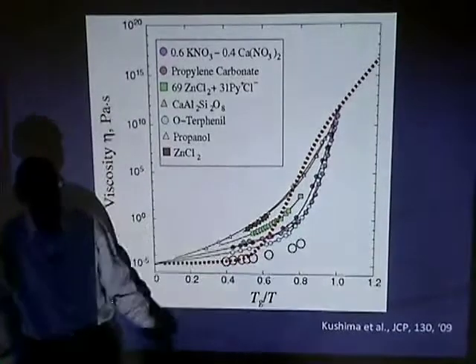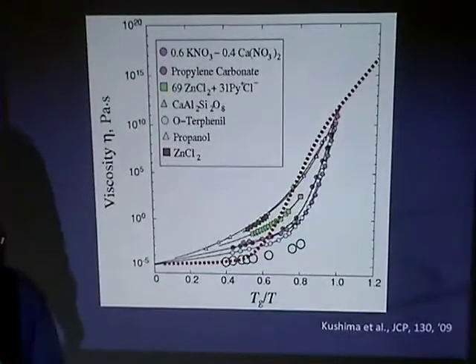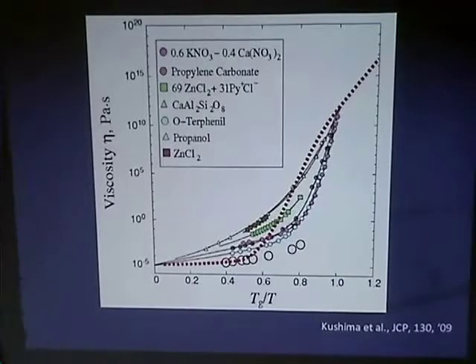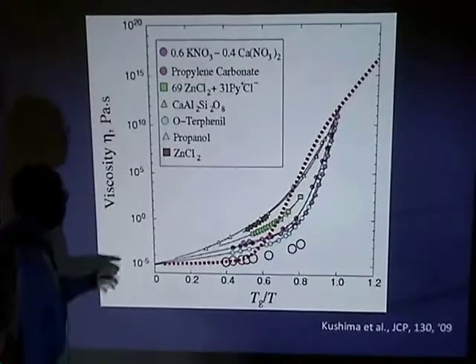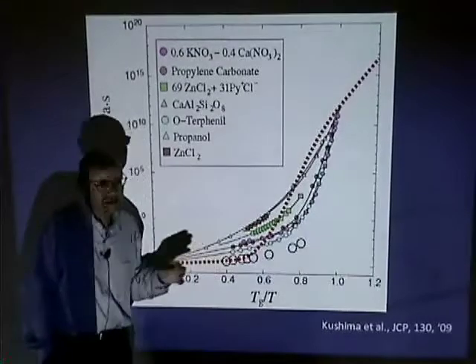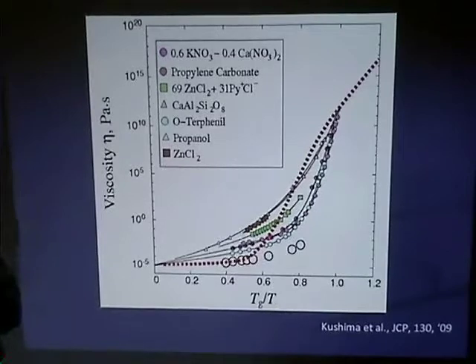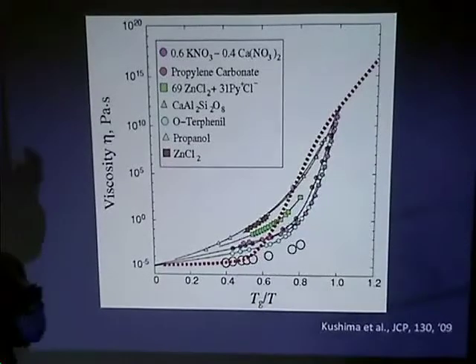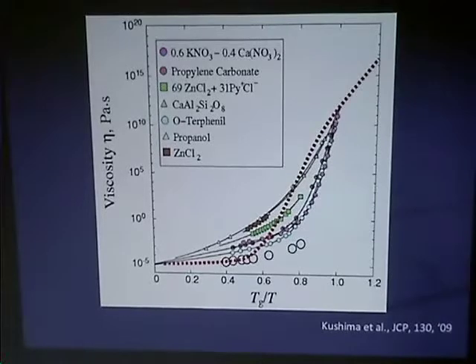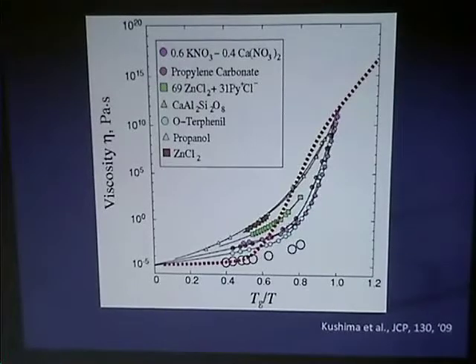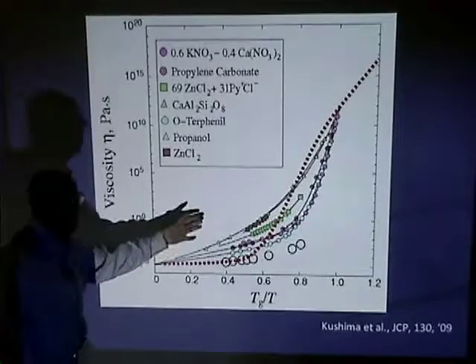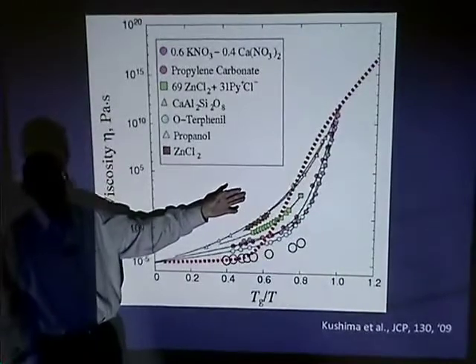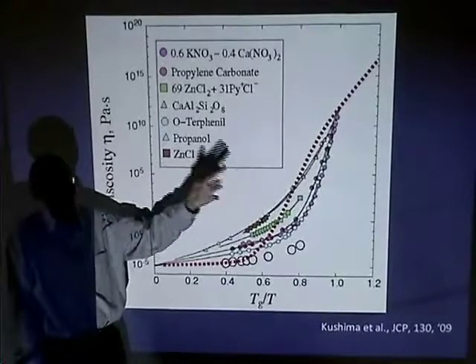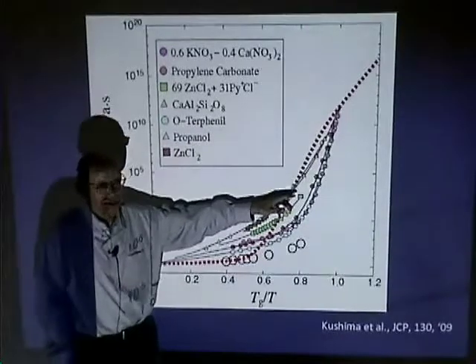Is that red dotted curve supposed to be what you see in equilibrium in the liquid, or is that falling out of equilibrium? The red dotted curve is based on sampling this transition state pathway using this method. Once you have the trajectory of this transition state pathway, you have to do considerable statistical analysis to extract the activation barrier, and once you have the activation barrier as a function of temperature, you get this curve. You don't have to make any statement about equilibrium or non-equilibrium - we can talk about that, but what's needed to arrive at this red curve is inherent structure.